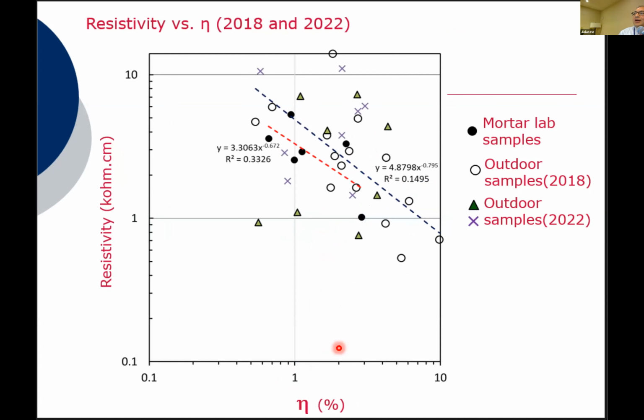And we also plotted the resistivity versus the eta value, and you see again that there is quite a bit of a spread of these values, and it is expected that in this case it's not really the concrete resistivity that we are measuring, but it's based on the presence of cracks that were in the samples where we did these measurements.